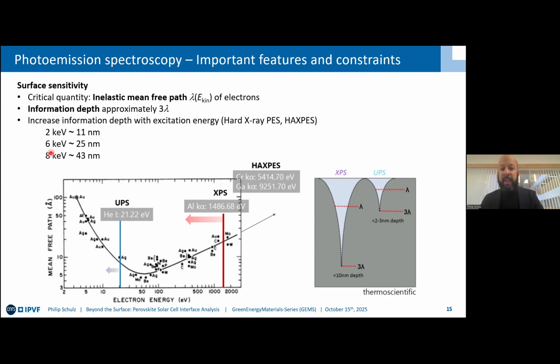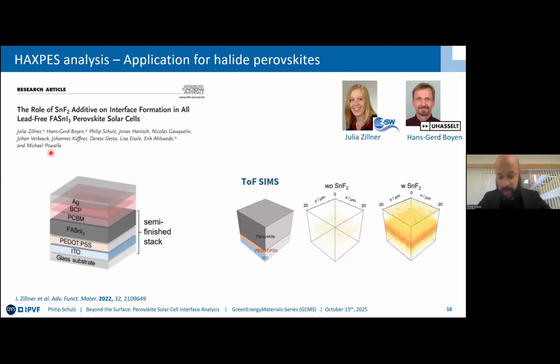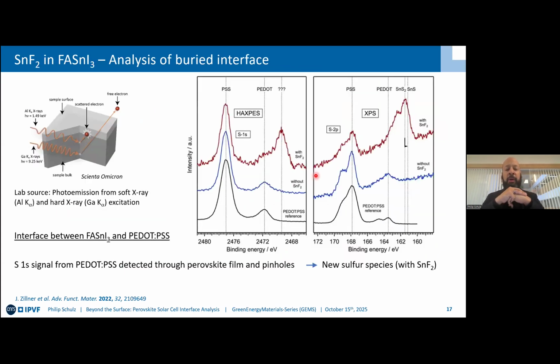And can you actually use this for halide perovskite research? Yes, you can. We actually did this on this example here for lead-free perovskites, formamidinium tin triiodide. In that particular case, what was known at the time is that, yes, you can put tin fluoride as an additive into your layer. It will make for better crystallization. There were some indications that it would aggregate at the interface, and we were able to show this also with ToF SIMS. But what was actually even more astonishing is when you now perform your photoemission spectroscopy experiment. XPS with an aluminum K alpha source. So here you are restricted to about 5 to 10 nanometers, and then the gallium K alpha source going down.